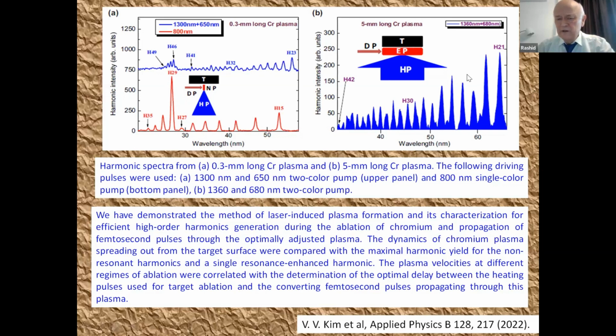A similar picture was observed in the case of generation in extended plasma. We generated both odd and even harmonics, however, we were not able to observe the resonance harmonic, due to quasi-phase matching conditions for this harmonic in the case of extended plasma. To overcome these problems, we use a multi-slit mask to create a few multi-jet plasmas to observe this resonance process.